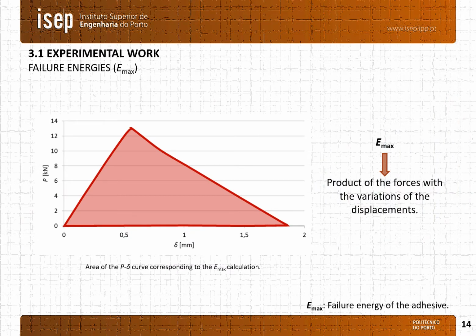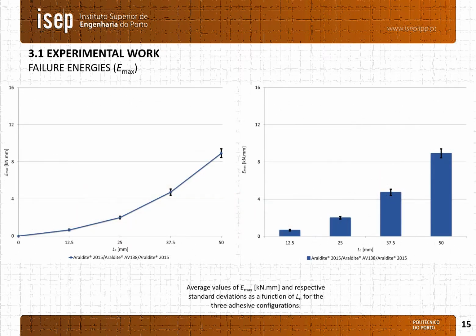The failure energy is obtained through the area of the P-delta curve. The maximum failure energy is the product of the forces with the variation of the displacement. Here it is possible to observe an exponential increase of the failure energy with the increase of the overlap length. Again, small values of standard deviation are obtained.